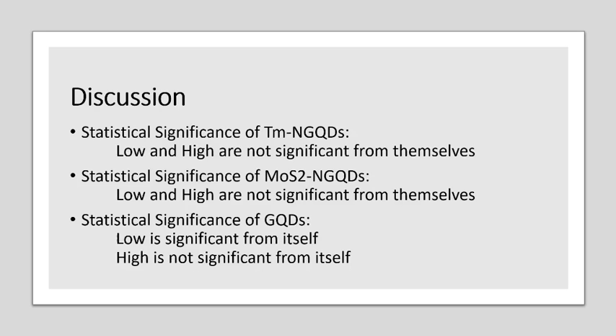For the high, for the molybdenum disulfide, we're also seeing the same thing. It would be much less, and there would be a greater statistical significance if that was the case. And with the GQDs, the high isn't significant from itself, but the low is significant from itself. So the idea that we're getting from this and what we're theorizing is that the low concentration is partially decreasing in cell viability due to the water and to the GQDs' effects. And the reason why the high isn't, we're thinking it's because it's just so toxic that we're not able to see the photothermal effect as much because the cells were going to die either way based on the toxicity of it.